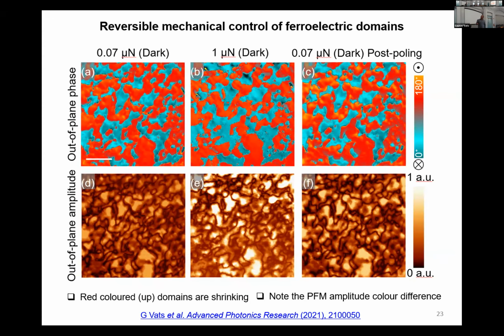Here, I acquired this image with 0.07 micronewton. No light was shining, in dark. I got these red and blue domains. And then I scanned the same area with slightly higher force, and you can see these red domains are shrinking. This is something similar to what we observed when we were doing optical poling. When I moved back to the lower force, it's returning. So the effect is reversible. From A to B, there is some change. B to C, there is some change, but A and C in principle look the same.